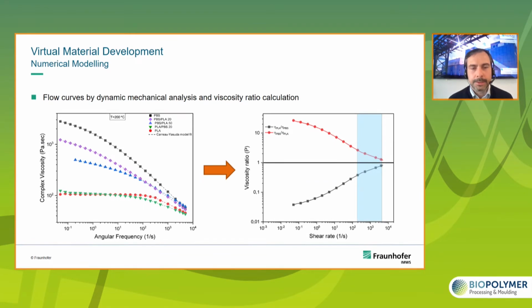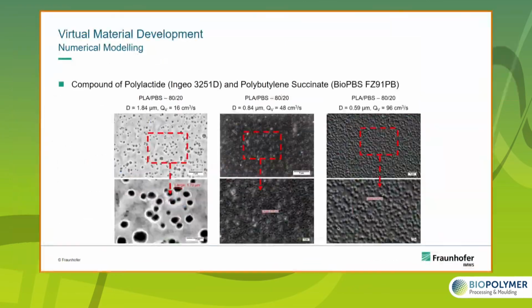mechanism. And this is very interesting for us because at injection mold or during injection molding, you have very high shear rates. And this means that during this processing, we will have variation in the microstructure. And this was also shown in the experimental results.